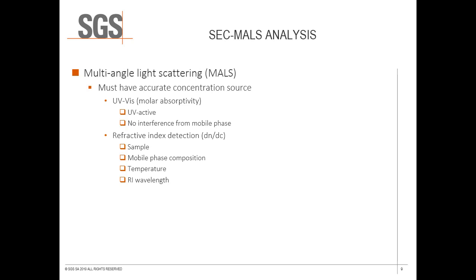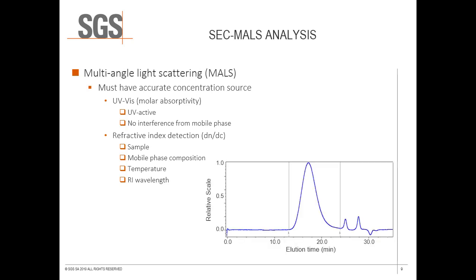It is often preferable for DNDC values to be measured under the exact conditions under which the analysis will be performed. The DNDC may be calculated from refractive index peak area, assuming 100% mass recovery, if the concentration is accurately known, no evidence of column adsorption or coelution interference is present, and the signal is strong enough to overcome any noise or wander in the refractive index baseline.